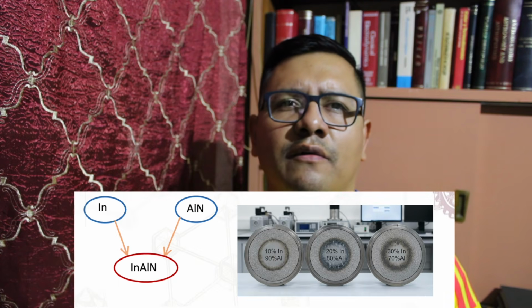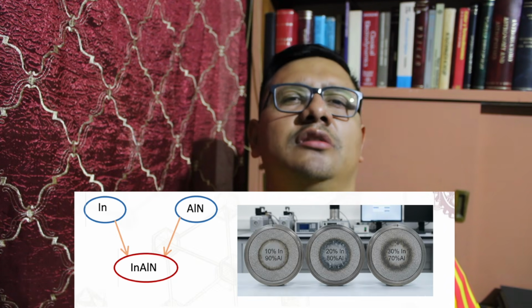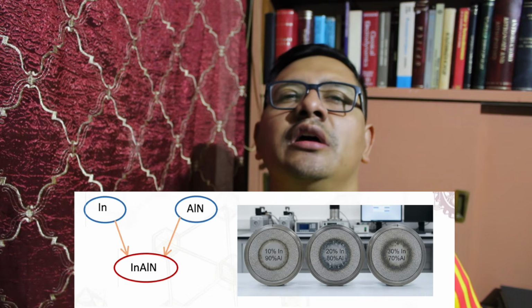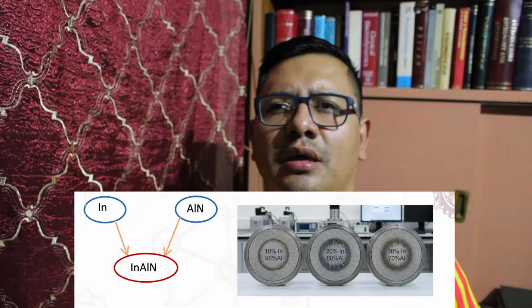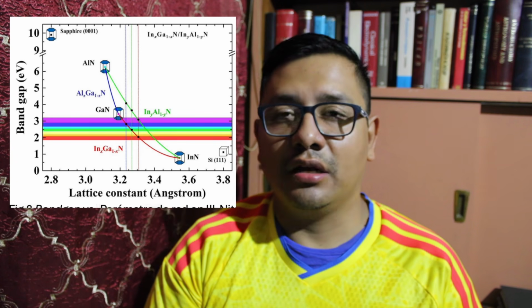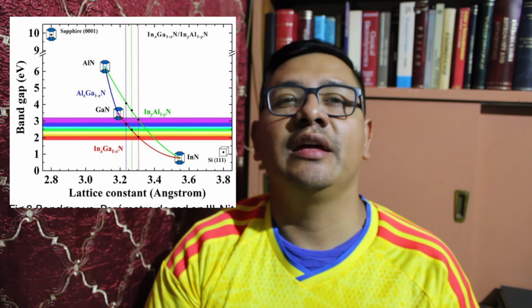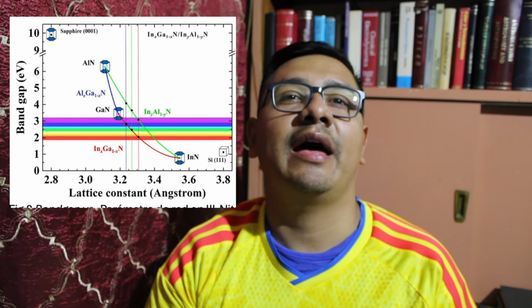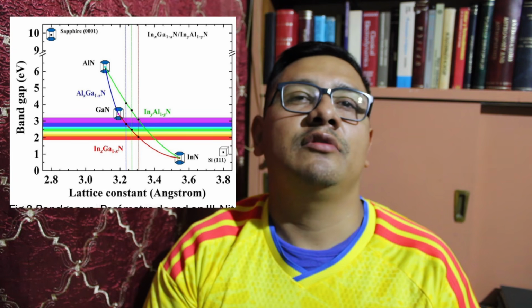In some variations, we changed this to a small target where we include a little composition of indium as an addition in order to show the modification of the band gap and the impact of the addition of indium in the target, in order to see the variation of the band gap adding indium to the gallium nitride lattice.